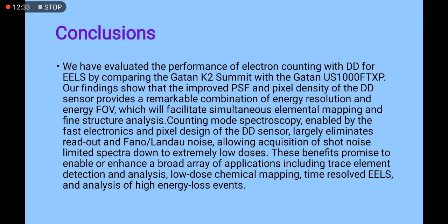Counting mode spectroscopy, enabled by fast electronics and the pixel design of the DD sensor, largely eliminates readout and Fano Landau noise, allowing acquisition of shot noise limited spectra down to extremely low doses. This benefit promises to enable and enhance a broad array of applications including trace element detection and analysis, low dose chemical mapping, time resolved EELS, and analysis of high energy loss events.